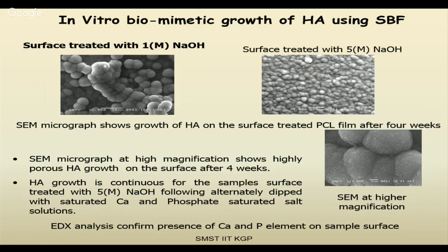So what we can see now, if we dip this into simulated body fluid, on the surface of the material in the laboratory, we can grow something like bone. That is very interesting. You can see that this surface, I think this was done for 30 days. So within 30 days, we can see very nice bone-like morphological growth in vitro, using SBF, simulated body fluid.